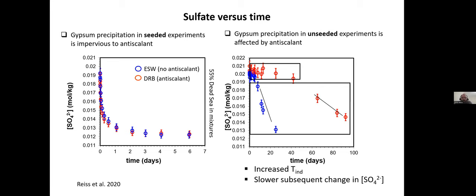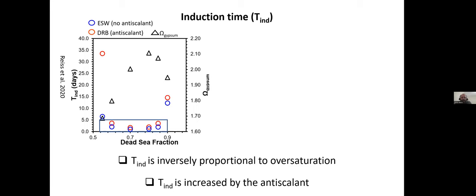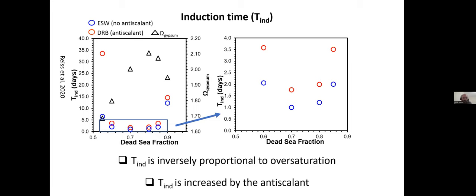So how does this work? I basically said there are three parameters that influence the efficiency of the scale inhibitors: the oversaturation, the pH, and the concentration of the inhibitor. Now, the variation of my pH in these experiments is negligible, so I won't discuss it. If we look at the induction times as a function of oversaturation in the experiments, we see there's an inverse relationship between the two. This means the more oversaturated I am, with or without scale inhibitor, the faster the induction time. But we also see that over the entire range of the experiments, the scale inhibitors extend the induction time.